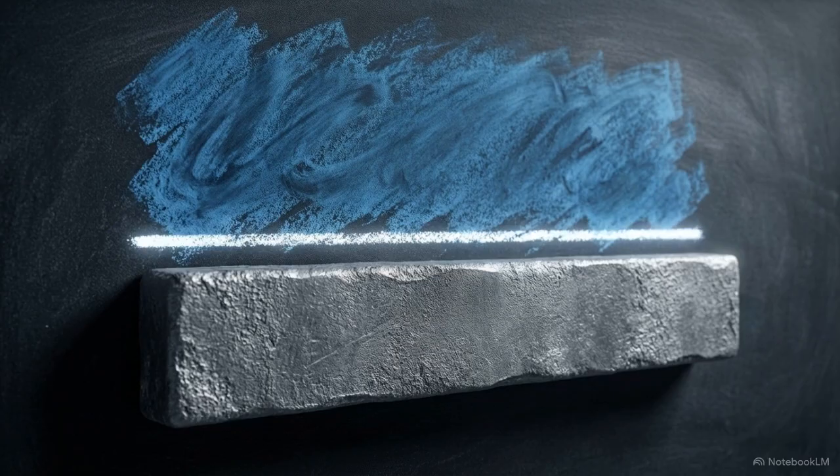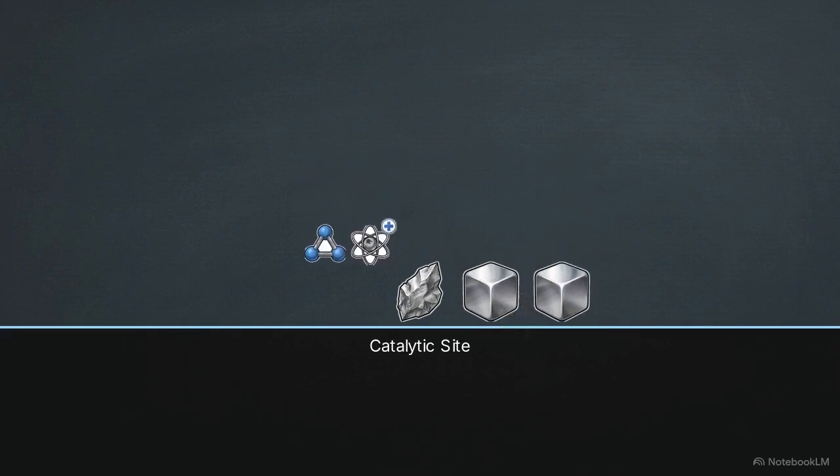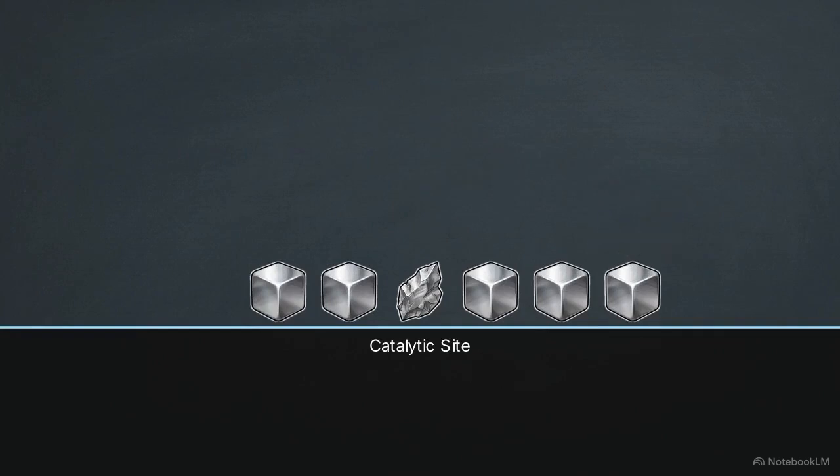The mechanism driving this process occurs at the microenvironment of the solid-liquid interface, the exact boundary layer where the bulk solution meets the bare substrate. A reducing agent oxidizes at the solid surface, liberating electrons onto the boundary. A dissolved metal ion captures these electrons, reducing into a solid atom anchored to the substrate. This new atom becomes a fresh catalytic site, drawing more ions to build a continuous lattice. This self-sustaining loop powers the chemical deposition, but because there is no external voltage to force the initial reaction, this sequence cannot begin if the starting surface is non-reactive.